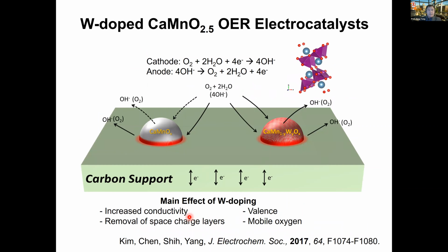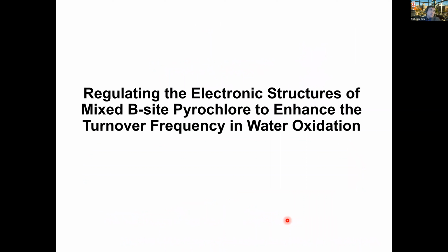Again, to summarize, the dopant of tungsten into this calcium manganate system increases conductivity and removes the space charge layers. And of course, we're also thinking the mobile oxygen could be a factor, as well as valencies. So these are the hypotheses we proposed based on the known measurements before in terms of conductivity measurement, and based on the known mechanism based on the electronic structure in that particular system. So in the remaining time, I'm going to show two cases that focus on B-site tuning.